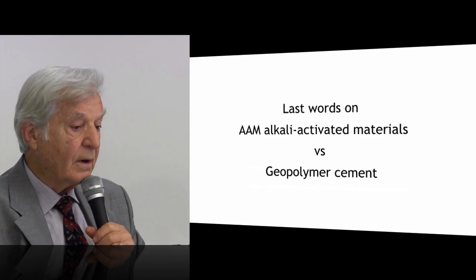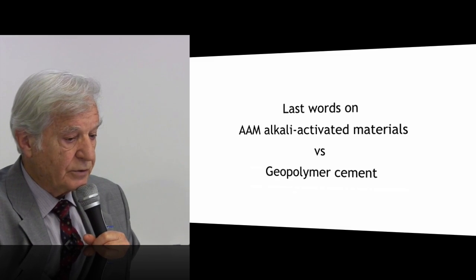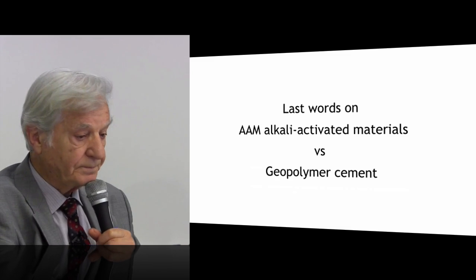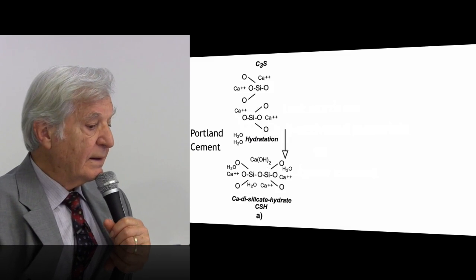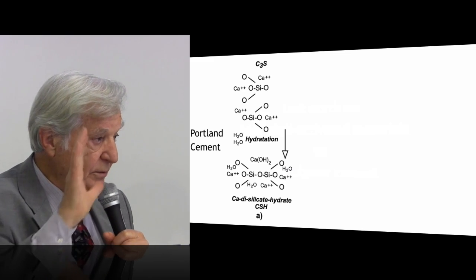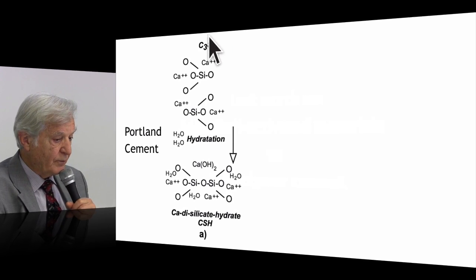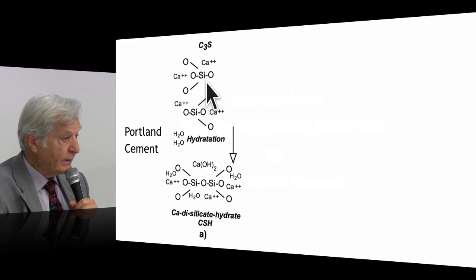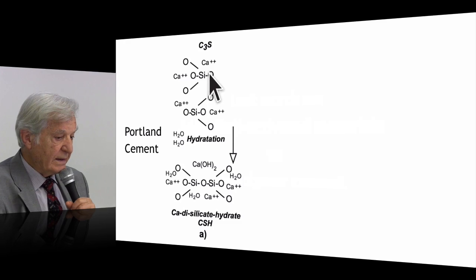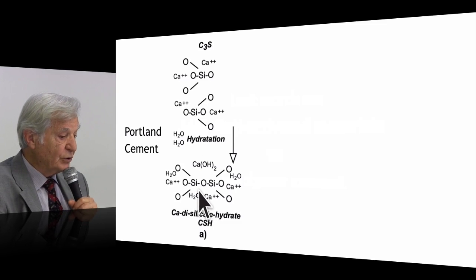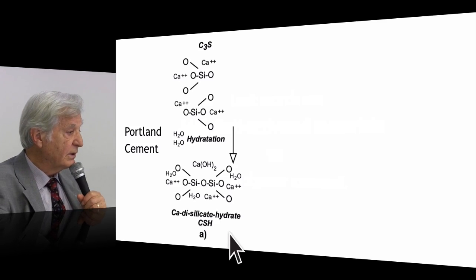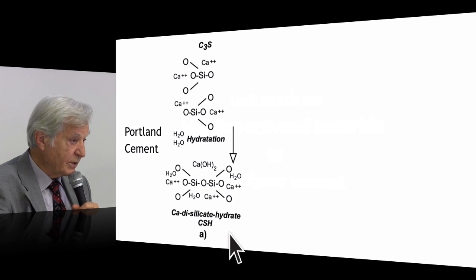So my last word, I hope, on alkali activated materials versus geopolymer cement. I repeat things that are well known, I hope now. This is the chemistry of Portland cement hydration. You are dealing with small molecules. This is a monomer, a monosilicate of calcium. This is a simple small molecule that is hydrated and generates the formation of a dimer, 2Si, calcium disilicate hydrate. This is the CSH of the cement scientist. Period.